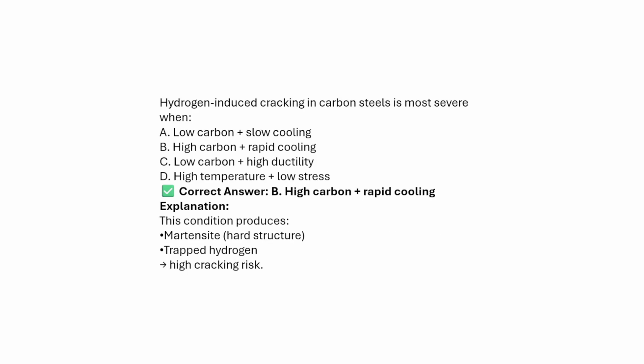Hydrogen induced cracking in carbon steels is most severe when: option A, low carbon plus slow cooling; option B, high carbon plus rapid cooling; option C, low carbon plus high ductility; option D, high temperature plus low stresses. The answer will be B, high carbon plus rapid cooling. This condition produces the martensitic phase and traps the hydrogen, which results in a higher crack risk.